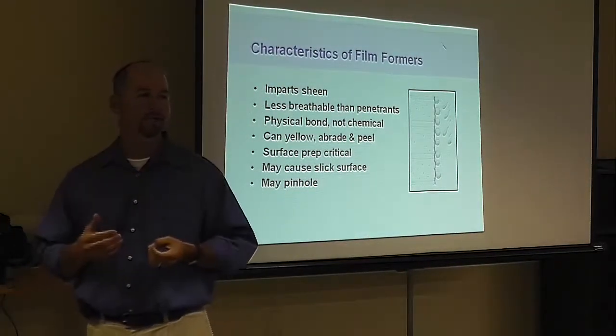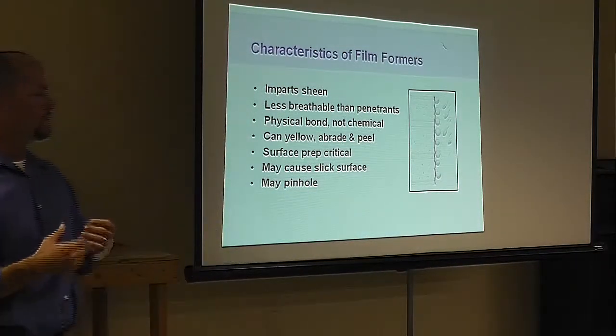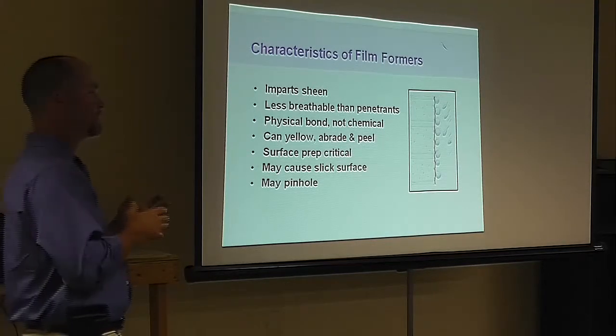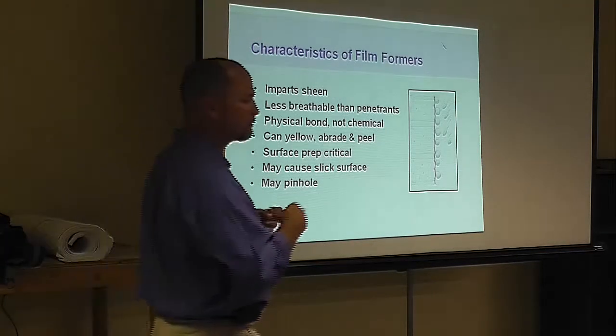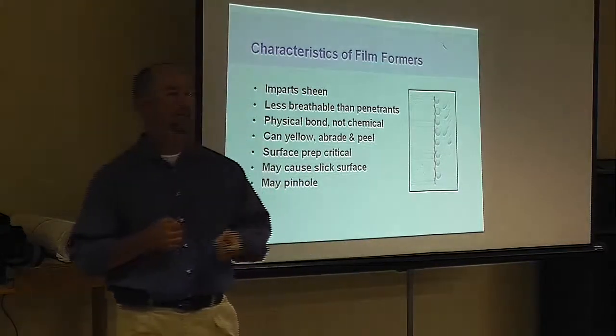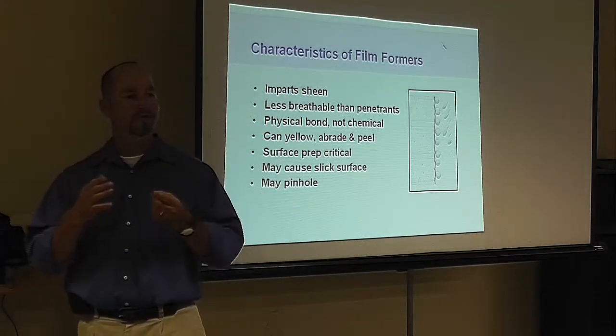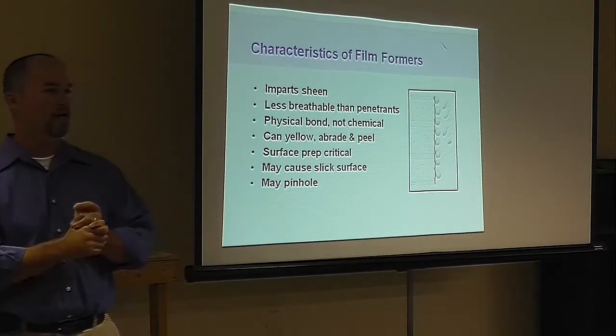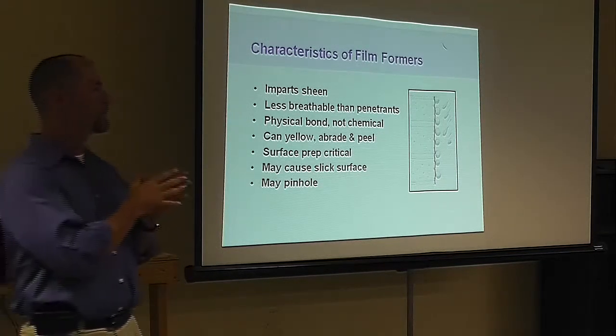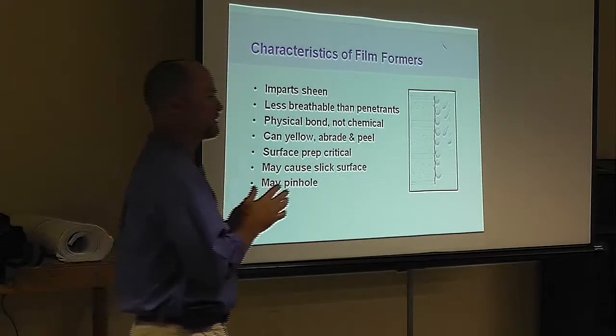They impart a sheen. They lay up on top. They're a physical bond, not a chemical bond. A lot of times, film formers or water repellents will change the aesthetics of the brick or stone. If you've got a light stone and a water repellent that's going to impart a sheen, a lot of times it turns amber or cast and has the potential to ghost. Your film former or water repellent doesn't allow moisture to travel in and out. It traps it in there.